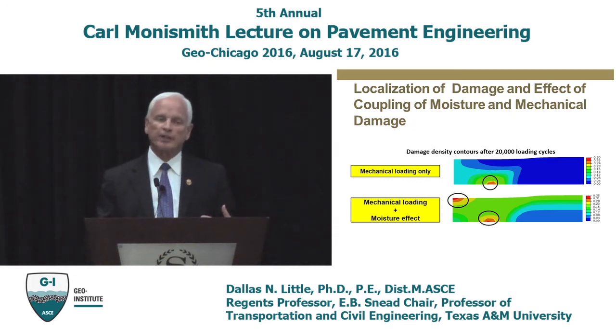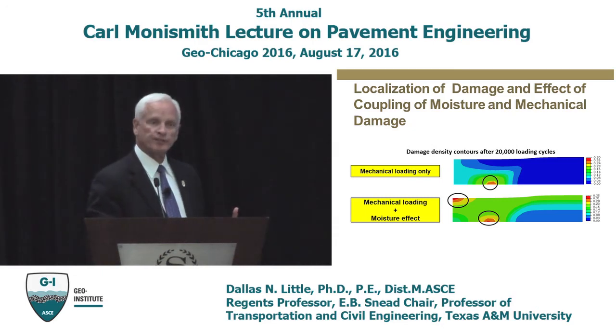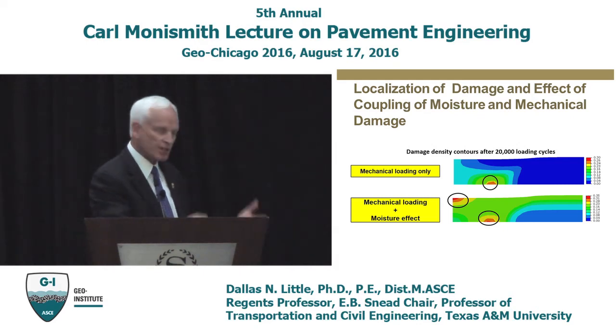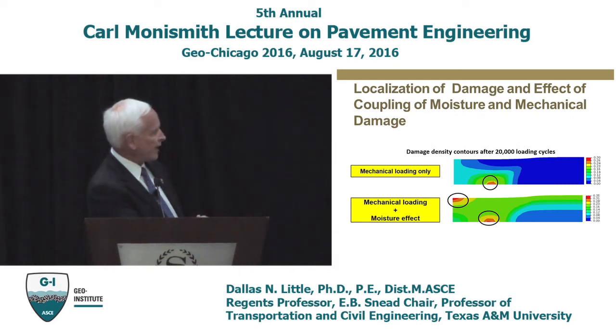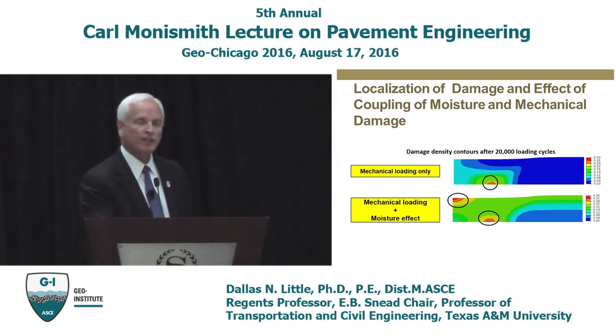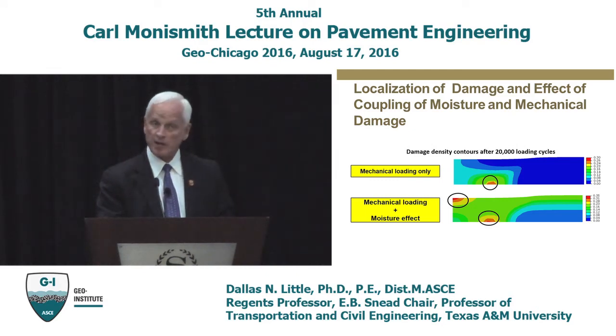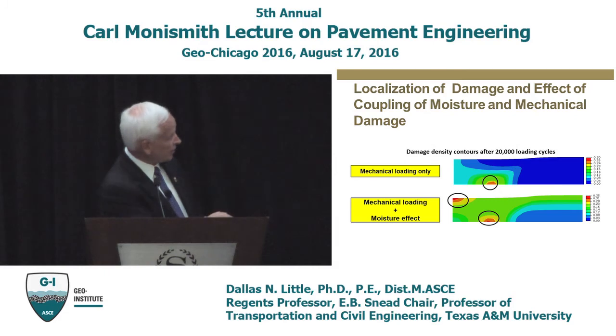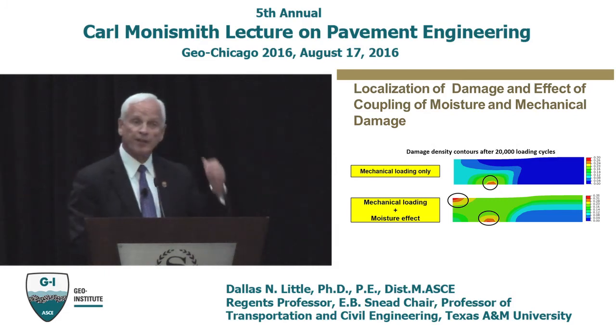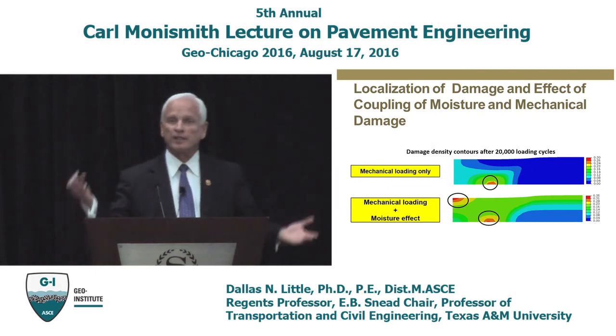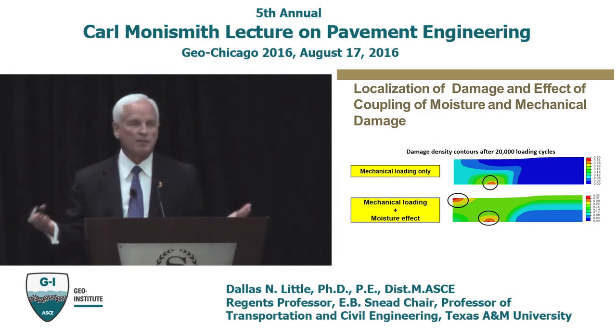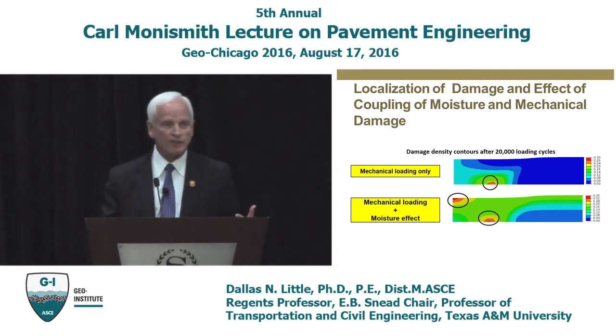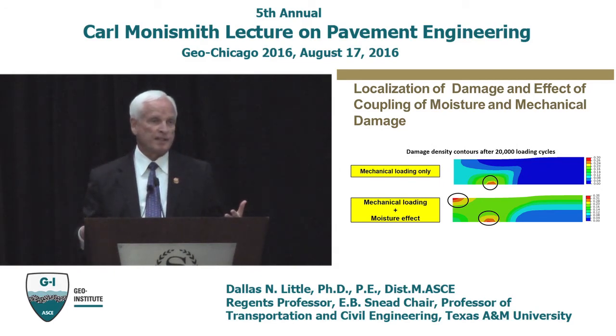But now let's couple in the effect of moisture softening because of diffusion of moisture. Now we have two localizations of damage, one near the bottom, one near the top. So this could be a bottom-up crack, and that could be a top-down crack. So this coupling of the environmental effects of moisture damage with the mechanical effects can be very valid. It's something that we really need to begin to focus on.